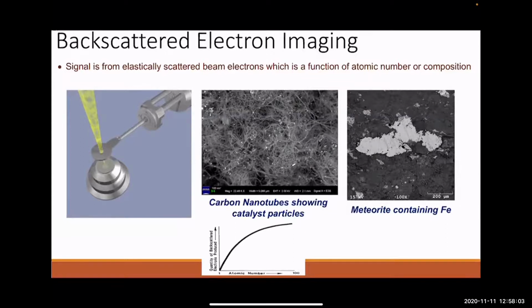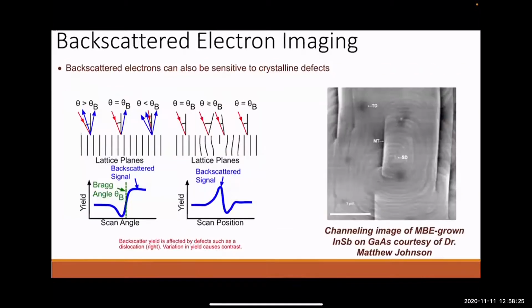This is another example where I looked at a meteorite with the backscattered image. For the most part, the surrounding matrix is aluminosilicate type structures, but there's also metallic iron, and you can see that popping out nicely. Iron's more dense than the surrounding material. So backscattered imaging is used for compositional analysis, or even if you're a material scientist involved with crystalline structures, you can get crystalline contrast too, and specifically defects in a crystal. So you can see what are called twinning structures here in a semiconductor material. So it's also useful for material science researchers who are looking at crystals.